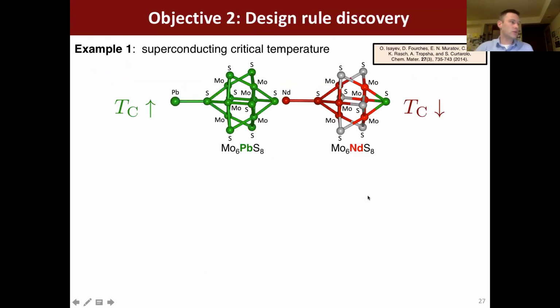Then we can also use the data to do design rule discovery. So here we have superconducting critical temperature. For example, when we did a study on the entire database, we found that placing lead at this site tends to increase the critical temperature, whereas placing neodymium at this site tends to lower the critical temperature.